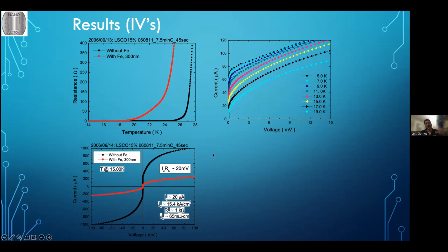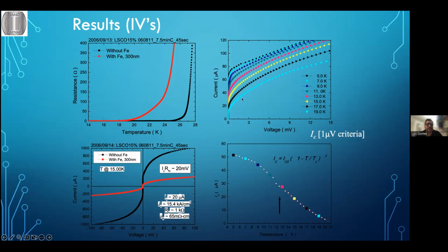These curves show a series of curves like this only for the first quadrant of voltage current. I have all the temperatures, but I'm only plotting a few of the points there, so you can see how the IV develops. Then I calculate the critical current as some kind of cutoff value in voltage, I measure that, and I plot it versus the temperature. So here are the VIs for every temperature. Out of this curve I get the critical current, and then I plot that as a function of temperature.